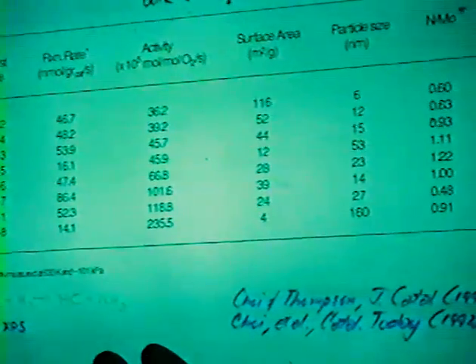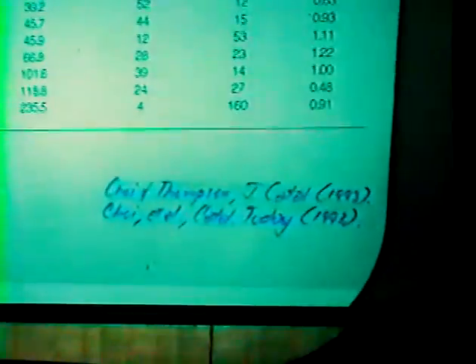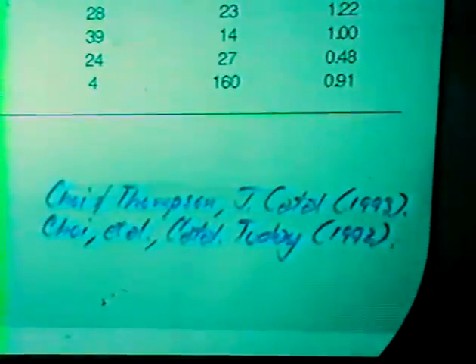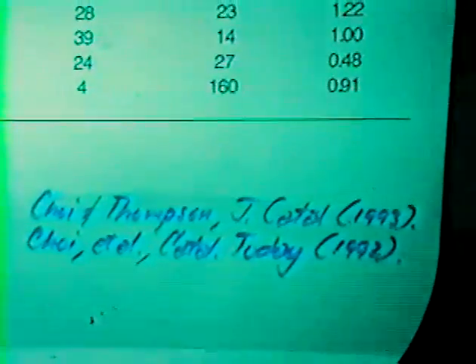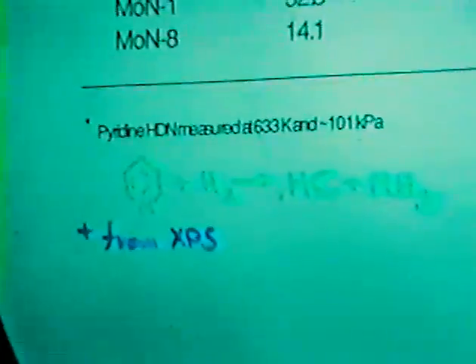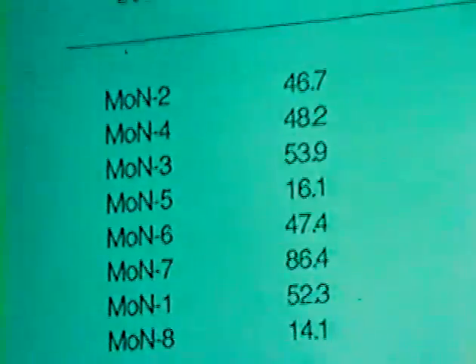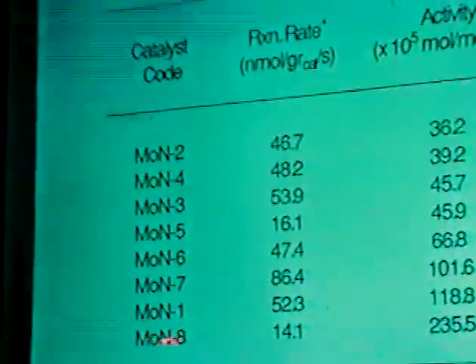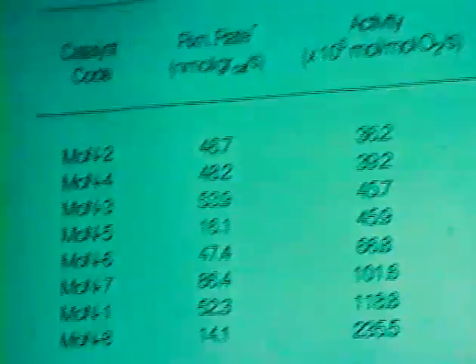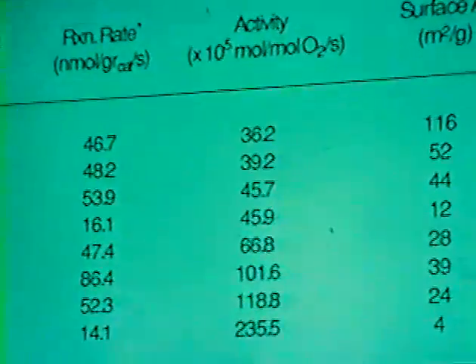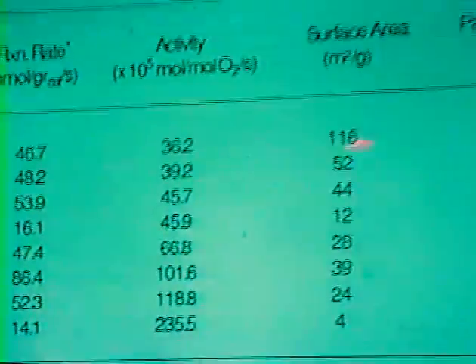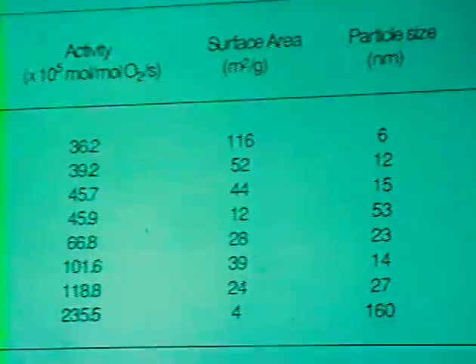As you remember, molybdenum nitride is very much like an alloy in the sense that it has two different elements. So we not only have to be aware of what the structure is, what the bulk structure is, but we also need to be aware of the composition. And so what we'd like to do is try and compare the catalytic properties with both structural and compositional characteristics. And this slide summarizes that.